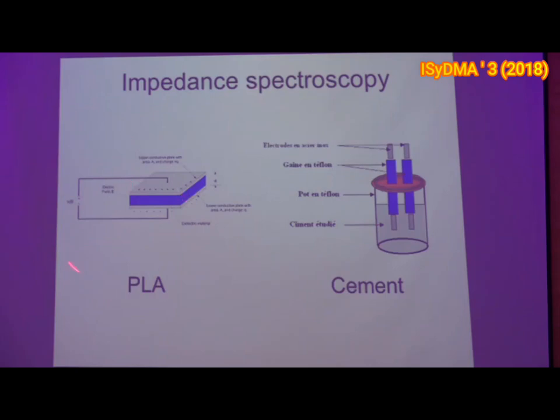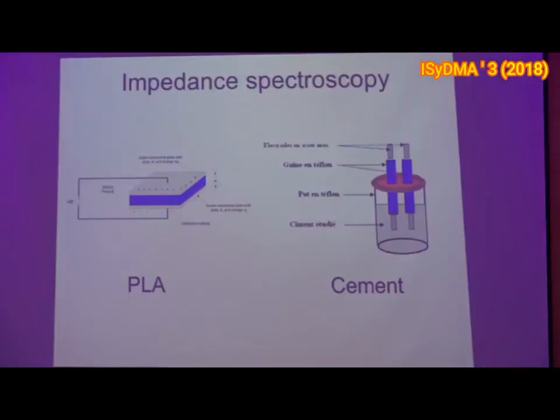So in the case of the polymer, I use this simple configuration, a parallel plate configuration. Here we have a gold electrode, a second gold electrode, and we put the polymer, that is a very thin film, about 100 microns, between these two plates, and I can see and calculate these four functions as a function of frequency and temperature, and during time. And we made this during about 1 month to see how this polymer is degraded with time.